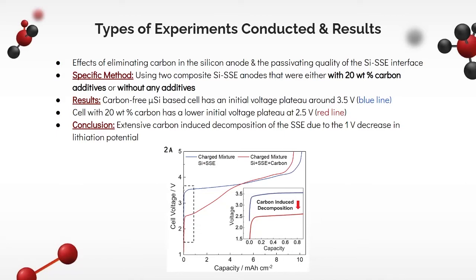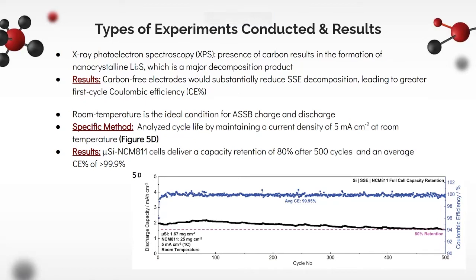The results have shown that the carbon-free cell has an initial voltage plateau around 3.5 volts. However, the cell with 20 weight% carbon shows a significant decrease, with a lower initial voltage plateau at 2.5 volts, thus revealing the extensive carbon-induced decomposition of the SSE due to the 1-volt decrease in lithiation potential. It's more preferable to eliminate carbon entirely in microsilicon ASSB system since there are less capacity losses. Another experiment was performed using X-ray photoelectron spectroscopy, indicating that the presence of carbon results in the formation of nanocrystalline lithium sulfide, which is a major decomposition product.